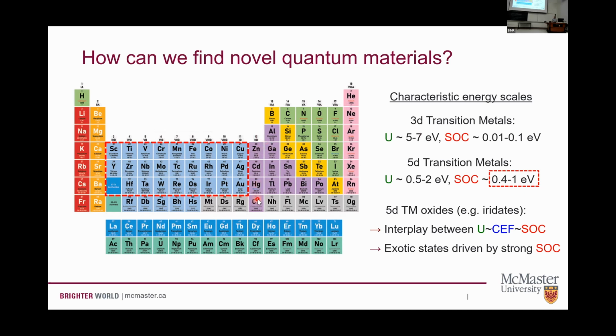As you move down the periodic table and you get into these heavier transition metals, the wave functions become broader, more spatially expanded. The elements become heavier. And so these electron correlation effects become weaker. So there's less overlap between the wave functions. And the spin-orbit coupling, which scales like the atomic number, becomes much bigger. So for these 5D transition metals, the energy scales that are set by the electronic correlations and the crystal field and the spin-orbit coupling, they're all about the same order of magnitude. And so you can get some interesting competition between these different energy scales. And it can be a great place to look if you're trying to find unusual or exotic states that come about because of this spin-orbit coupling.